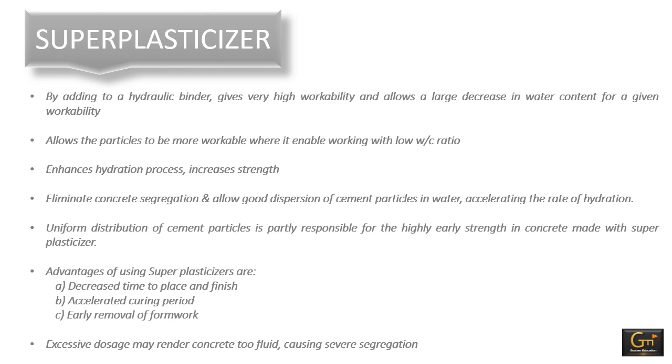Now why are superplasticizer admixtures used? At a given water cement ratio, this admixture increases the workability, typically by raising the slump from 75 mm to 200 mm. The second use of this admixture is in the production of concrete of normal workability but with an extremely high strength.